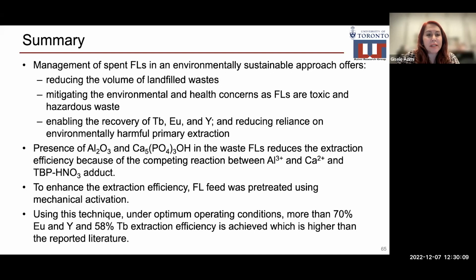We observed that the presence of aluminum oxide and calcium phosphate hydroxide in the waste fluorescent lamp reduces the extraction efficiency because of the competing reactions between aluminum 3+ and calcium 2+ ions and TBP-HNO3 adduct. To enhance the extraction efficiency, we pre-treated the fluorescent lamp feed using mechanical activation. Under the optimum conditions, more than 70% europium and yttrium and 58% terbium extraction efficiency is achieved, which is higher than reported in literature.